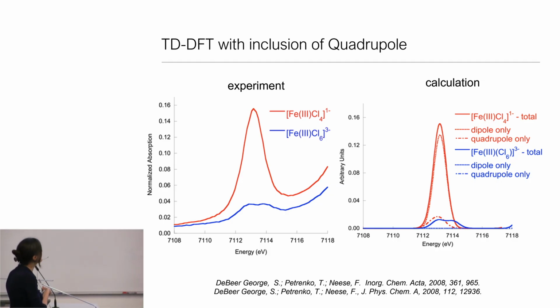And what you can see is that these pre-edges that we talked about, going from the octahedral to the tetrahedral limit, not only do you beautifully get the trends in ORCA, but you can also really break down the quadrupole and dipole contributions and nicely see, as we discussed, that in octahedral ferric hexachloride, that is a quadrupole only contribution, where the dipole here is a flat line. And this all comes straight out of the calculations you guys will be doing this afternoon.